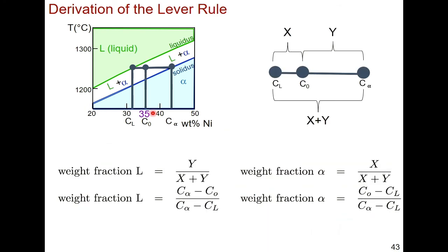Okay, so you can mathematically work out why this is. I mean, if you've ever been on a seesaw, right, you know that the heavier person will be lower to the ground. So if you want 2 people to be at the same height, you can just change the weight, or you can change the center of mass, right, where you put the anchor of the seesaw, which you can't do as a 5-year-old, I realize, but you can imagine doing that for this, okay? So if you have Cl here, C naught and C alpha in your tie line, if you take the length, C alpha minus C naught, divided by the total, which is C alpha minus Cl, you get the phase weight fraction of L, which is over here.